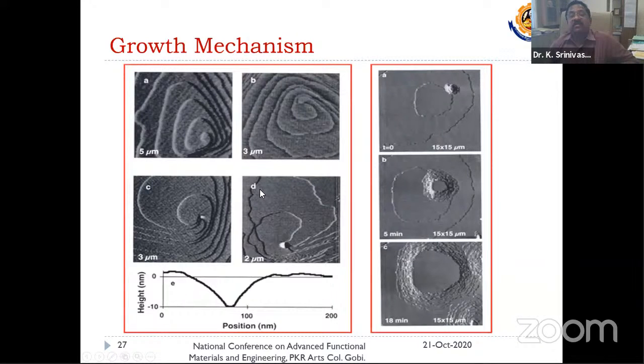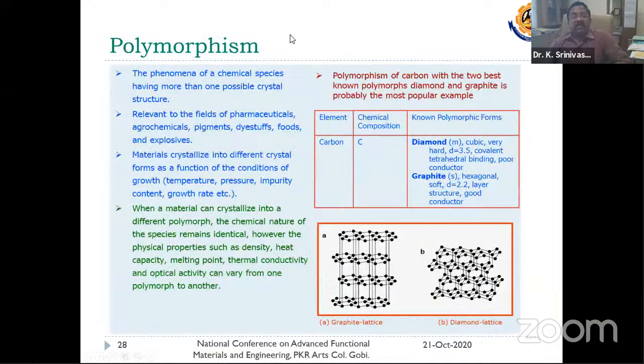Otherwise, you will get spurious nucleations, non-controllable nucleations on the surface of the growing crystal that will spoil the single crystalline nature of the material. That will induce more defects into the crystals. When there is a defect, definitely that defect will affect the perfection of the crystal and also the property of the crystal, and finally the efficiency of the devices fabricated out of the crystal. So the crystal growth process is very, very important and dedicated process. More than a science, it is an artistic process.